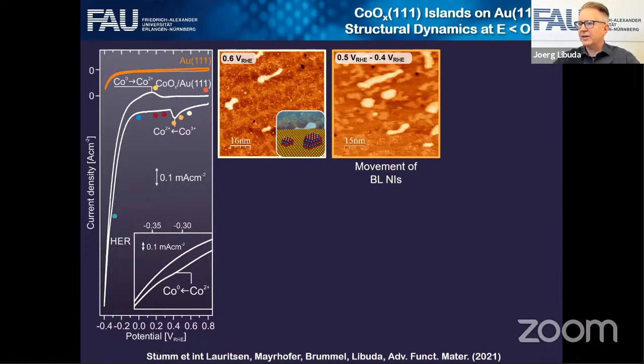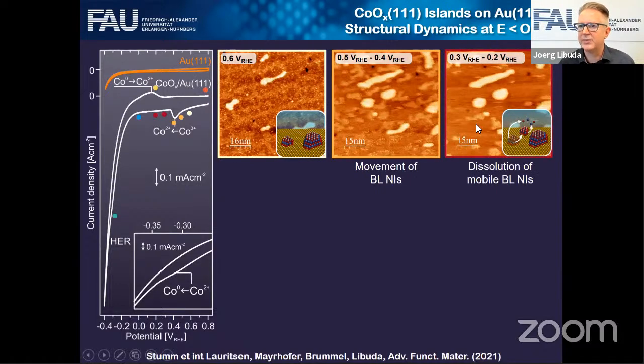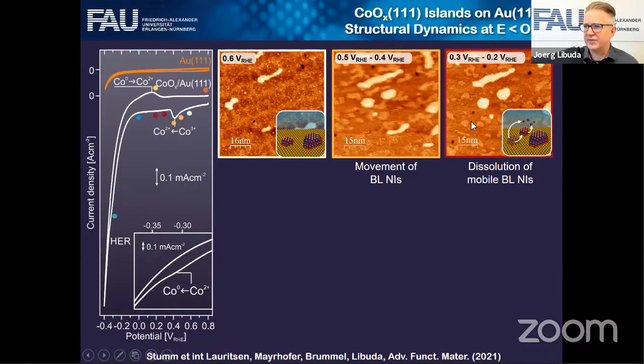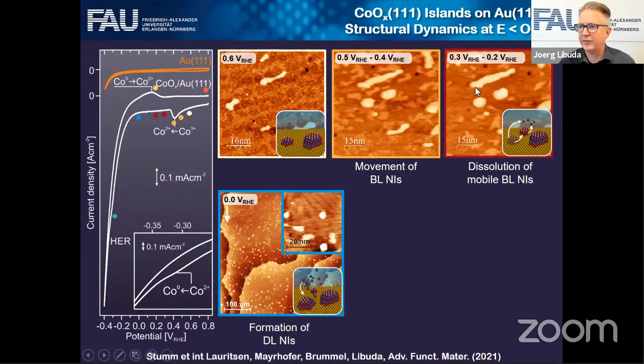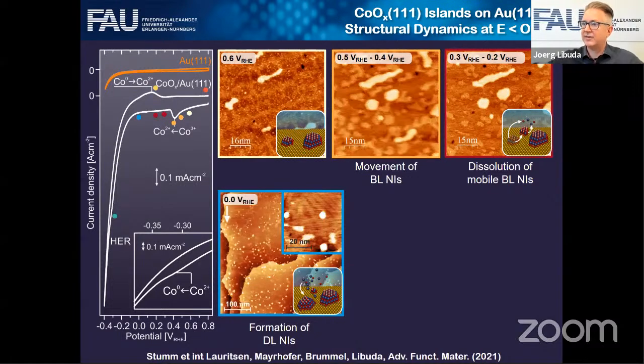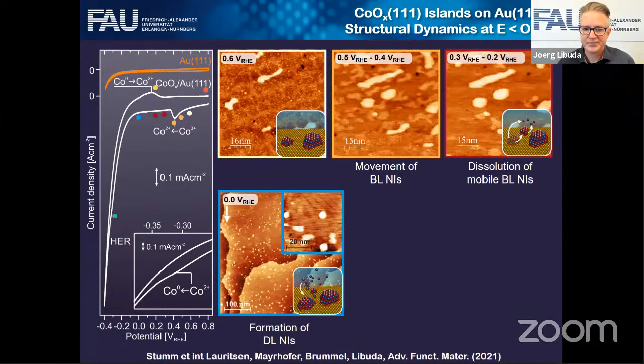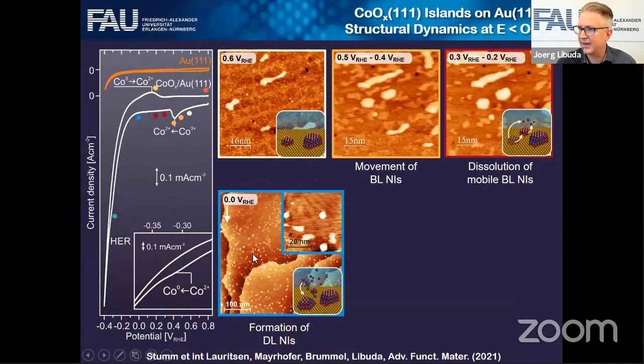So apparently cobalt becomes mobile, desorbs, readsorbs, and then the ions really change their structure on the surface dynamically. So we get a very dynamic surface. And then if you further decrease the potential, these islands dissolve, and at the same time, they really move over the surface. Very dynamic situation. These double bilayer islands are still there. And if you further decrease the potential, we actually have redeposition of these double bilayer islands. So we have more of these islands. We again readsorb cobalt on the surface.